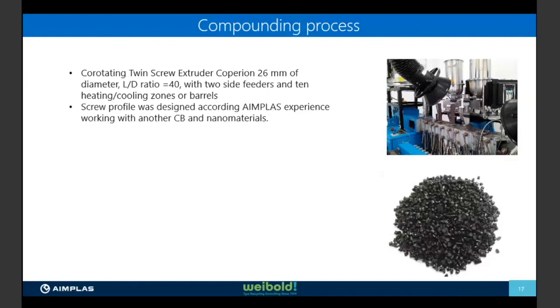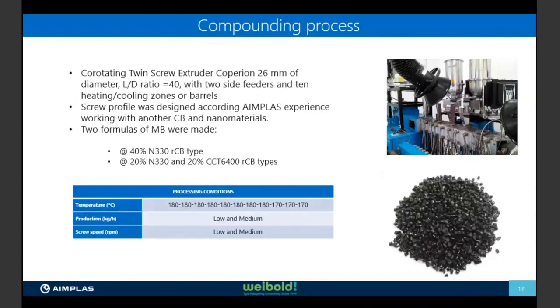You can see here in the right side down samples of the master batch that we obtain. And of course, we work at 40% of carbon black, and we have N330 and a combination of this N330 with the recycled carbon black. Here there is a mistake. The first is not recycled carbon black, it is commercial and virgin carbon black. Okay. So we compared those combinations with one master batch commercially available that was delivered by one big player. And that's the conditions of our experimental design.